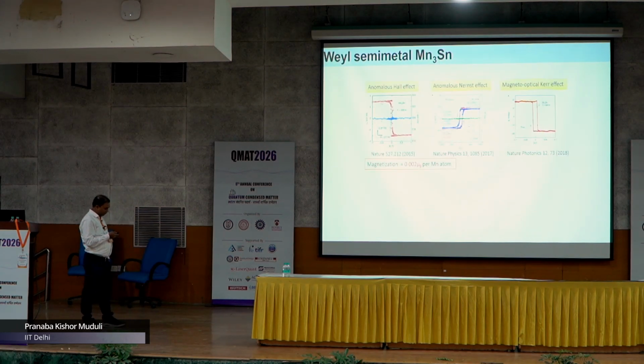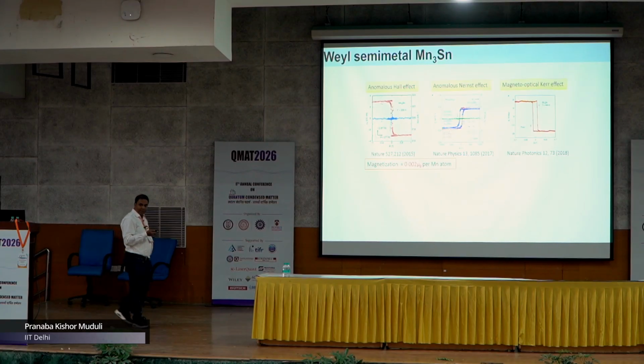Now, also this is still an antiferromagnet. So, in an antiferromagnet, you expect that there is no anomalous Hall effect, Nernst effect, and magneto-optic Kerr effect. But these three things are normally observed in ferromagnets with finite magnetism. But in this material, despite being an antiferromagnet, you see these three things: anomalous Hall effect, Nernst effect, and magneto-Kerr effect.